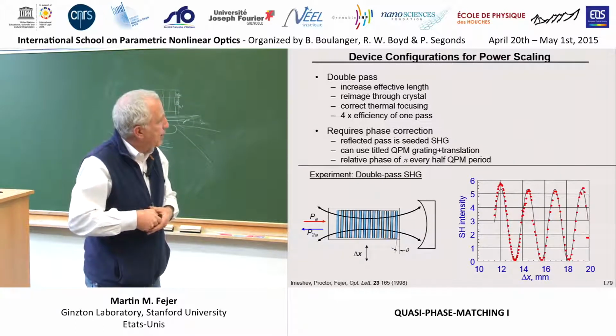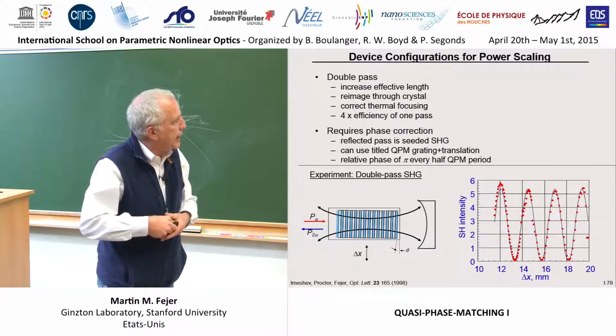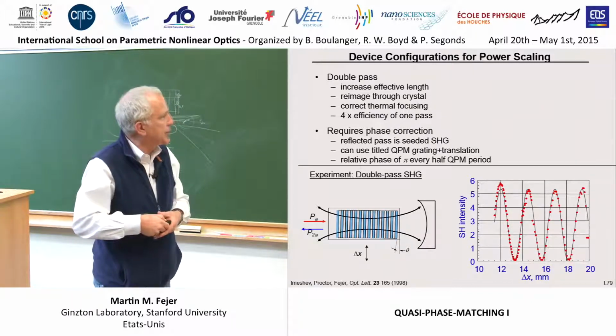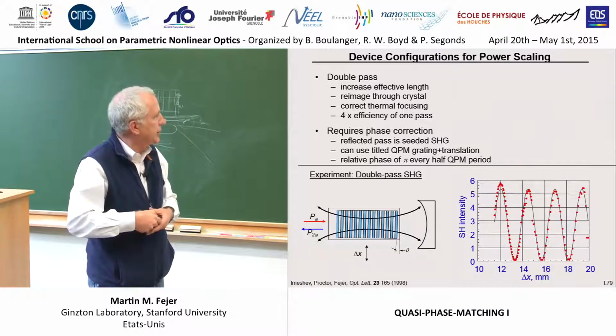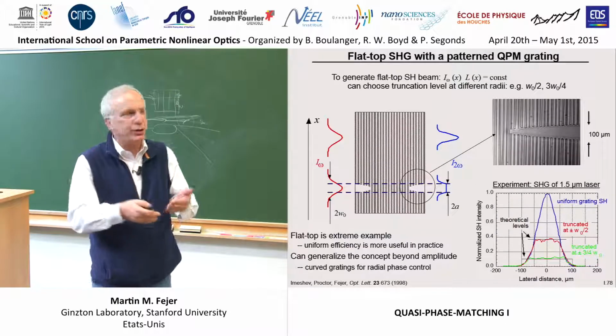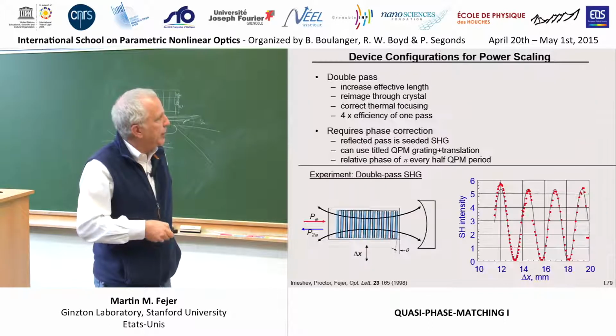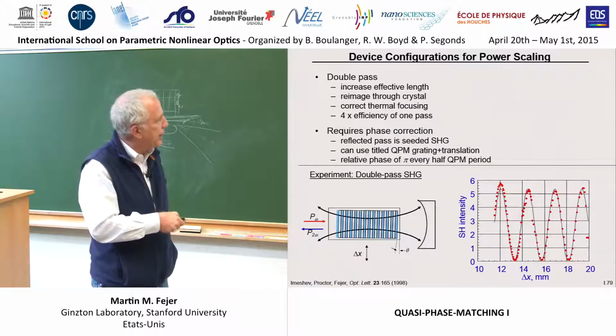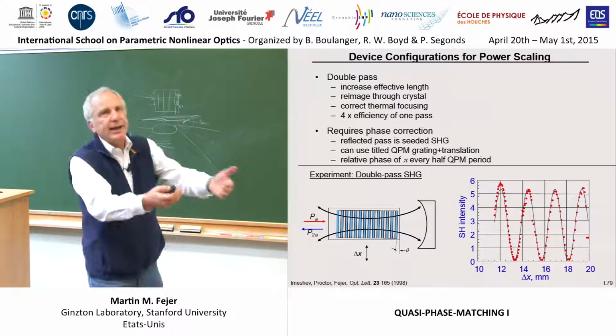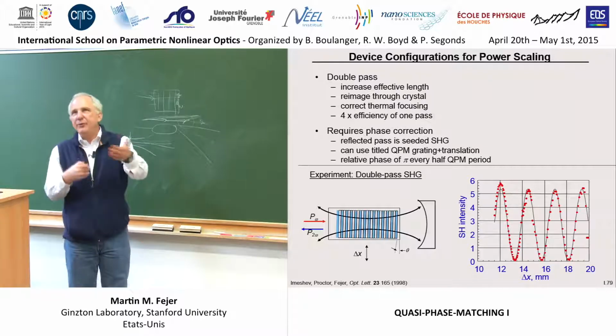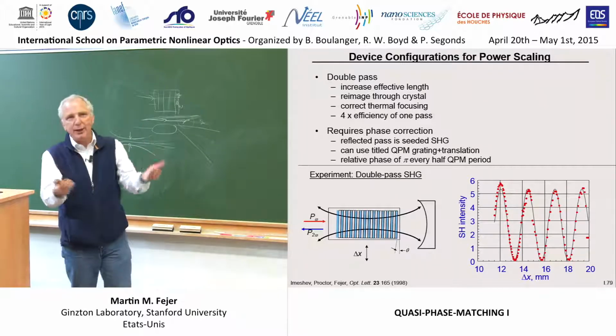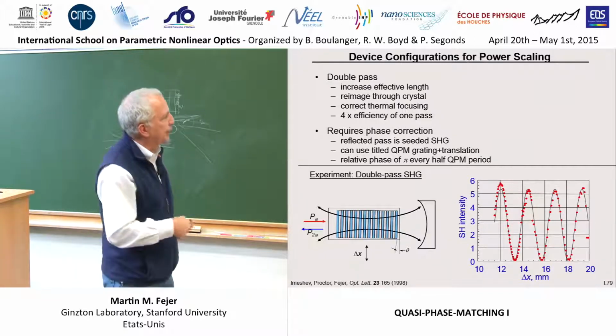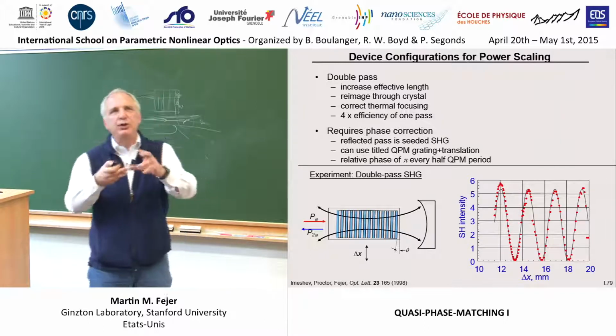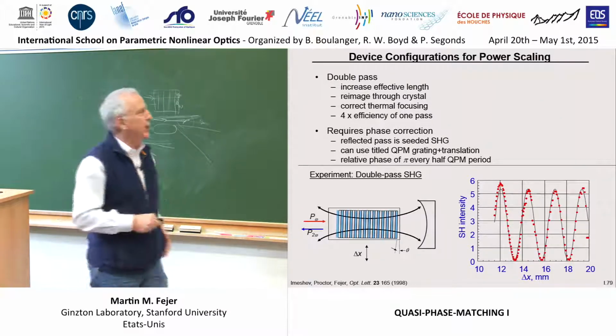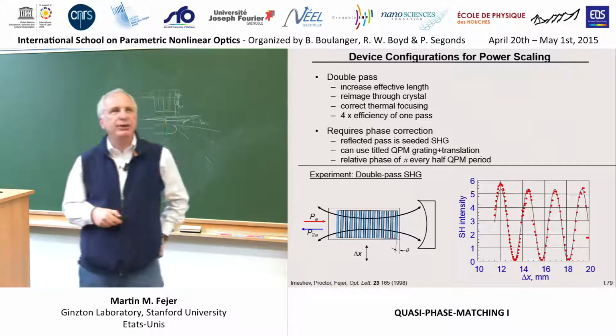As Majid pointed out, as you go through this medium and bounce off this mirror, you get some phase shifts between the fundamental and the harmonic, and maybe there's some air dispersion or something. Then when you come back through this structure on a second pass, the second conversion path may add in phase, out of phase, or at 90 degrees in phase to the forward path, and you need some means to control that if you really want to have a double pass device operate efficiently.